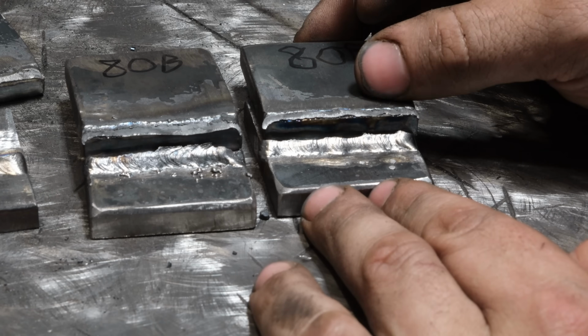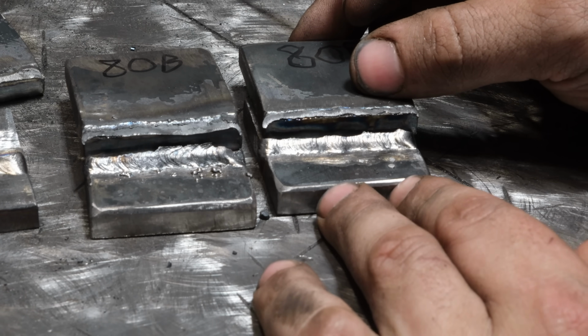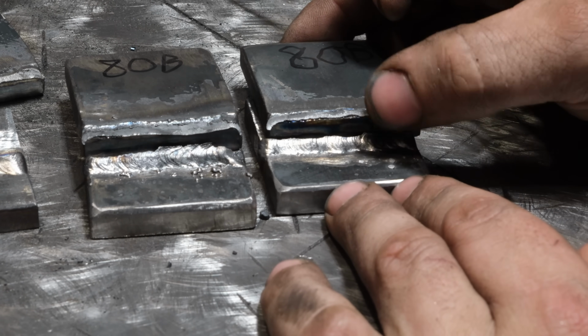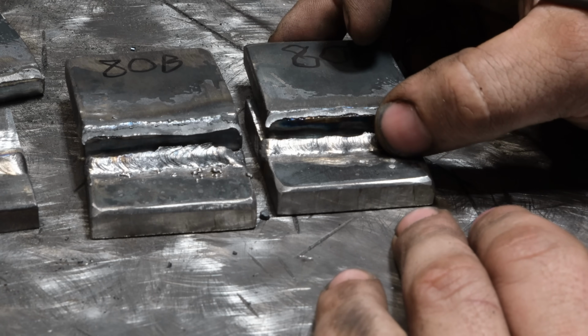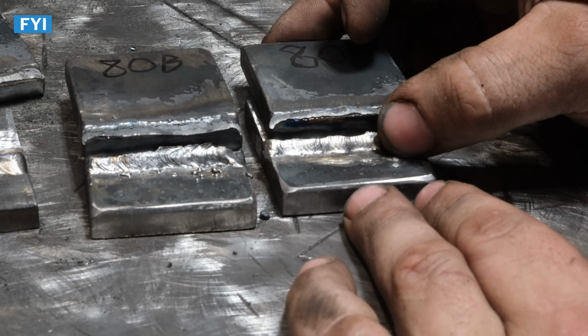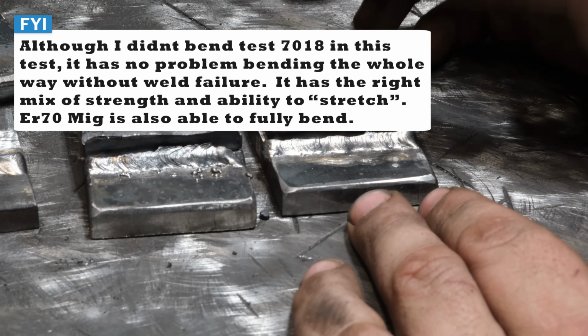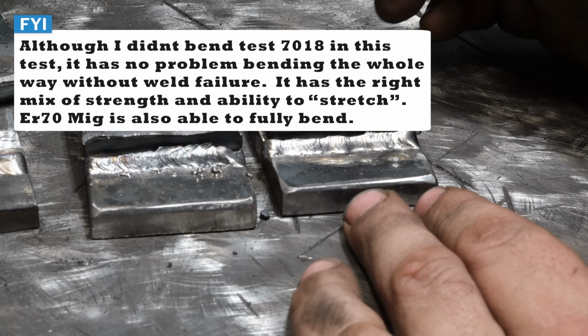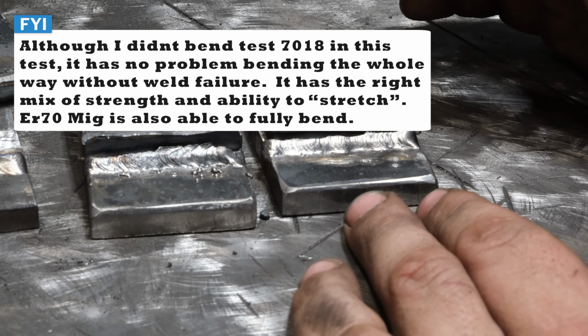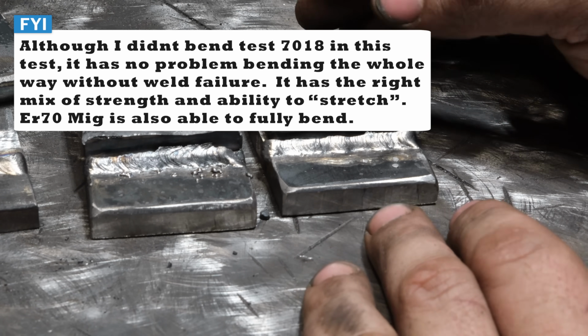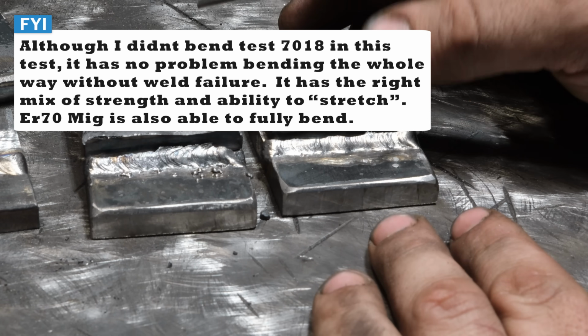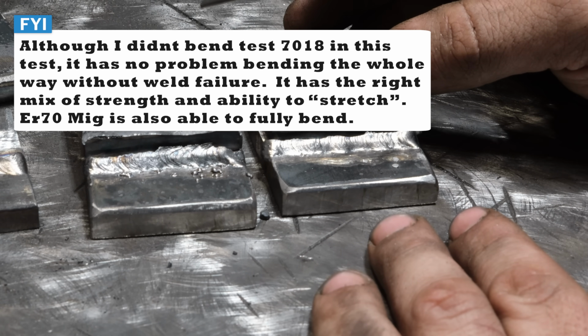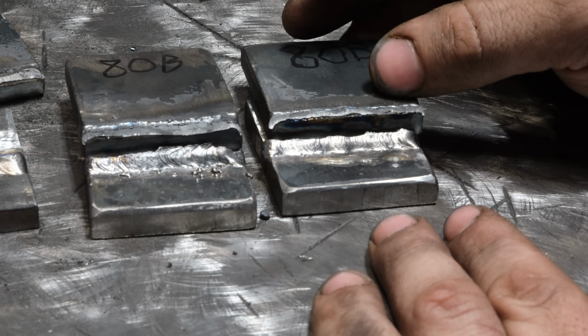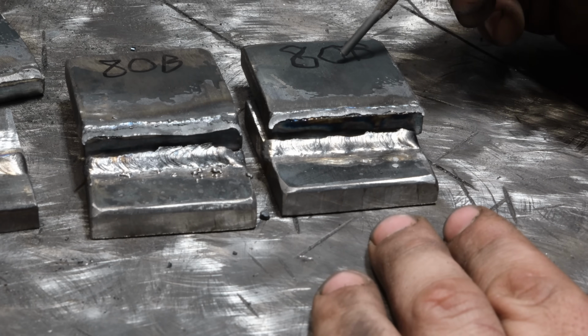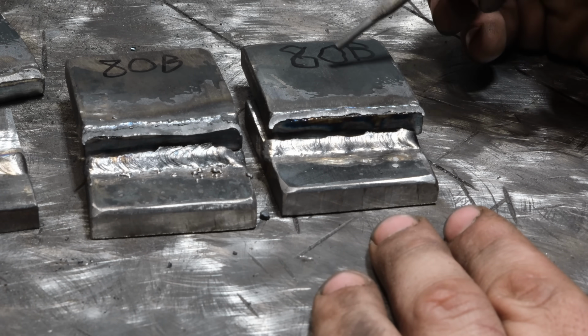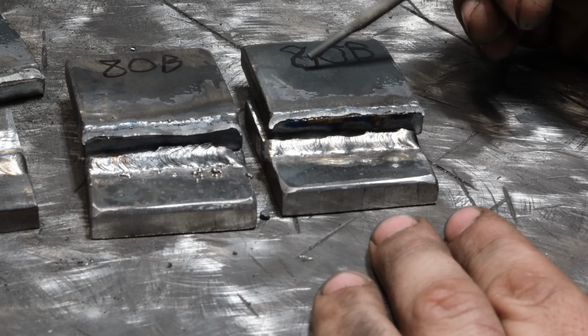So I would say this rod, the welded deposits is pretty brittle. Now the question is, okay, this is an 80,000 PSI tensile strength. Is it better than 7018? No. And one of the funny things that you might be shocked to find is that 70,000 is the minimum testing strength. The actual results of most 7018 rods put it well over 70,000 PSI tensile strength. So this rod, in reality, could be weaker than 7018.